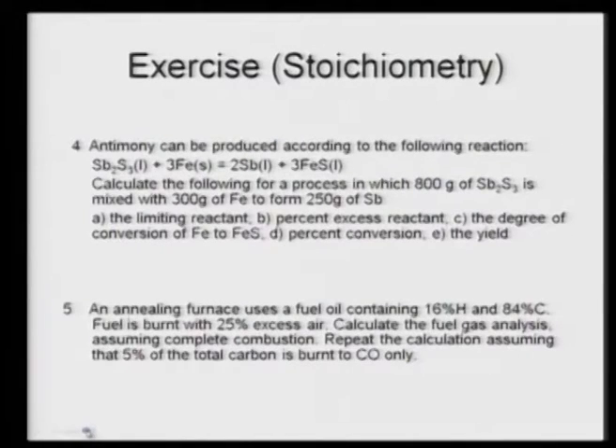Problem 4: antimony can be produced according to the following reaction. The reaction is given to you. Now, you have to calculate the limiting reactant, the percentage excess reactant, the degree of conversion of Fe to FeS, the percent conversion, and the yield, when 800 grams of Sb2S3 is mixed with 300 grams of Fe to form 250 grams of antimony. Here you will note that one of the reactants is lower than the stoichiometric proportion, and that will clear the concept of limiting reactant.